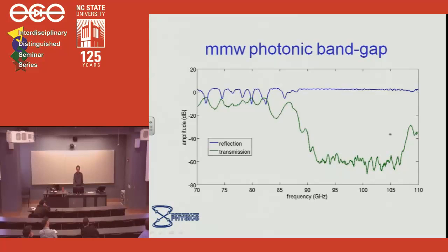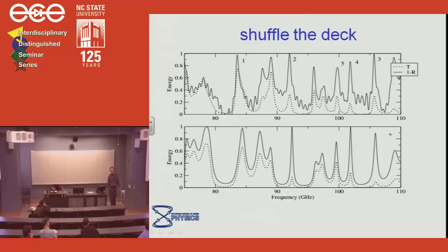Now, so this is for a periodic system. Now what we do is we shuffle the deck to make a random system, and what you see is really striking. Let's see. These are calculations down here, and these are actual measurements up here. And what you see are these modes where the transmitted field, so this would correspond, for example, to a band gap, where the transmitted field goes down basically to 0, but then zooms up, goes down to 0, and then zooms up. So you see these modes in which there is enhanced transmission, okay, in this random system.